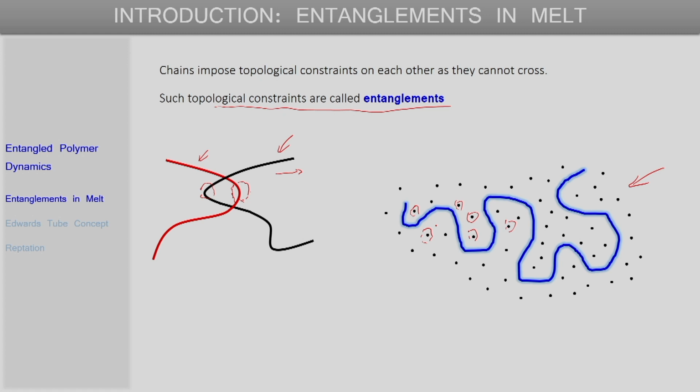and one way to accomplish that could be that if we consider this as the tail end of our polymer chain, then the motion might be thought of as starting where the tail retracts in a way. So, this part of the tail retracts so that some kind of loop or kink is formed, still respecting the constraints imposed by the surrounding chains, and this kink or loop is then moved along the contour of the entire given chain all the way towards the head of the chain, which may be here, and while moving it is respecting all the constraints that are imposed by the surrounding chains.